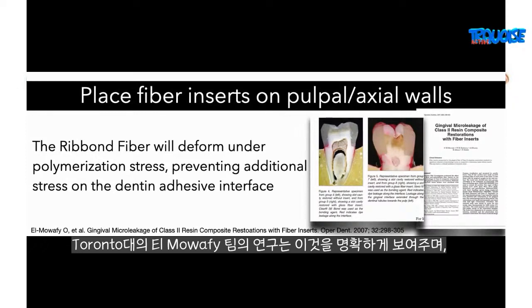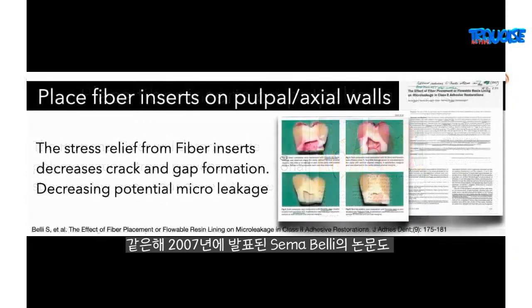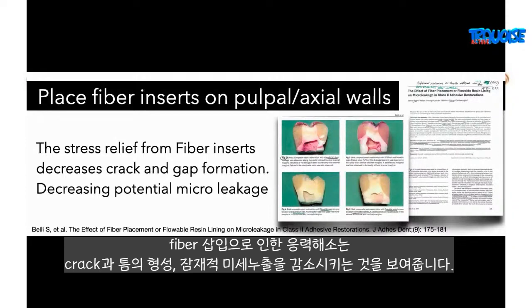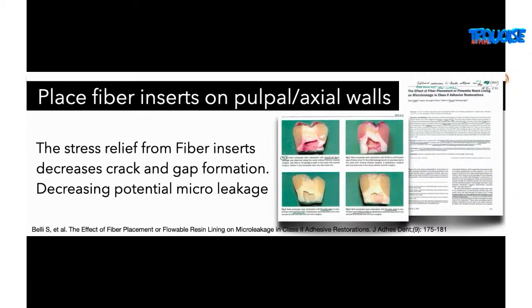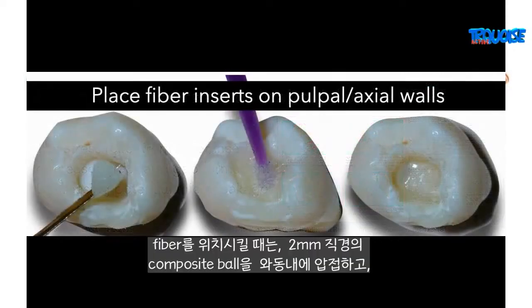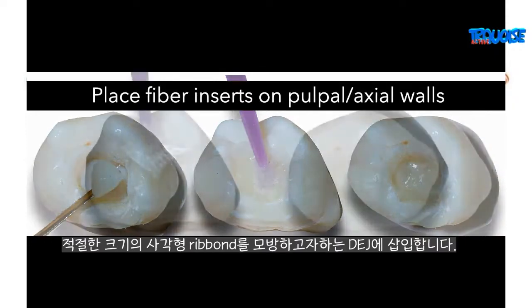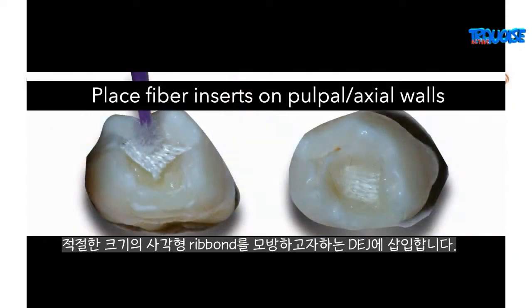This research done at the University of Toronto by El-Mowafy and his group showed this very clearly. And this paper in 2007, the same year, by Sema Belli, again showed that the stress relief from fiber inserts decreases crack and gap formation and decreases the potential microleakage. So when we place fiber, we use a thin increment, a 2 millimeter diameter ball of composite, compress that into the cavity, and then we take a ribbon square of appropriate size and press that in. You're mimicking the DEJ right now.